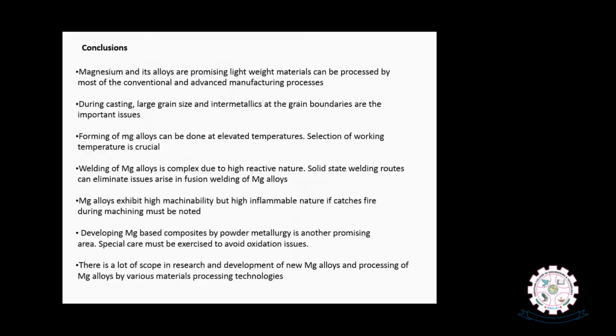Then overall conclusions: magnesium alloys are promising lightweight materials which can be processed by most of the conventional and advanced manufacturing processes. During casting, magnesium alloys can be cast at various temperatures. Selection of working temperature is crucial in metal forming of magnesium alloys, and welding of magnesium forms oxide layers. Therefore, solid state welding routes can be used, which can eliminate the issues associated with the fusion welding of magnesium alloys. And magnesium alloys exhibit high machinability but are highly inflammable if they catch fire during machining, which must be noted while selecting the appropriate coolant.